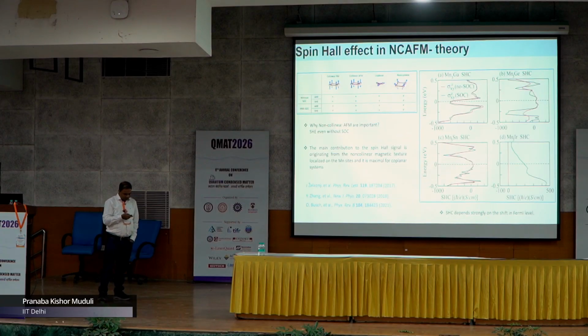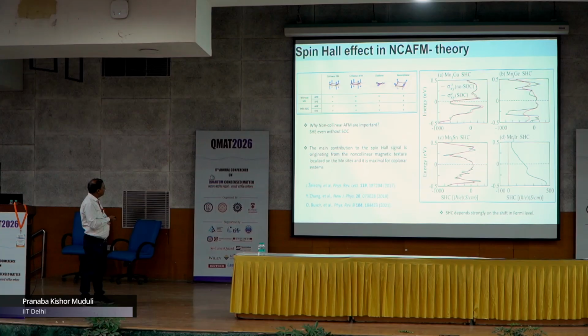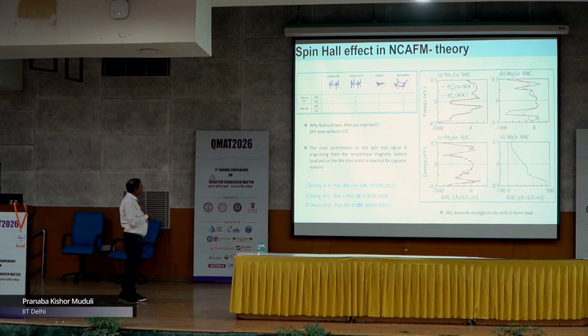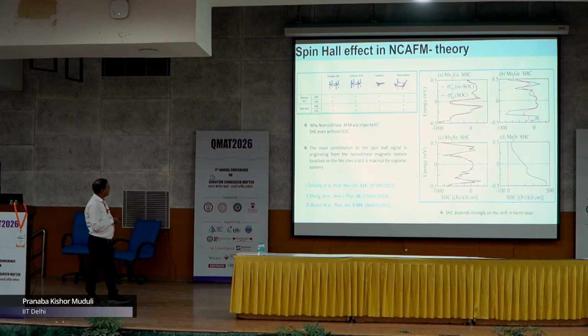Now, I will go back a little bit in the literature, back in 2017, where it was also predicted that this material will also exhibit a normal spin Hall effect apart from the magnetic spin Hall effect. So, this was from a theory paper. They calculated the spin Hall conductivity for several materials including Mn3Sn, and they found that there is a finite spin Hall conductivity in this material, and this is arising from the non-collinear nature of this material system.